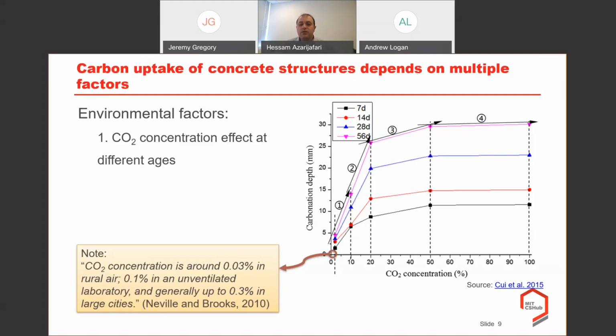So if you would like to have a good representative model for estimating the carbonation, we definitely need to set up our experimental test in these conditions, but for a longer period of time, because we know that at this CO2 concentration, we may have difficulties to observe a significant amount of carbonation.